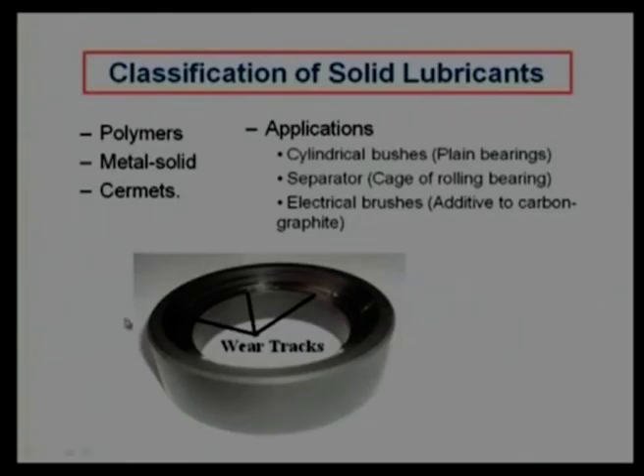When we talk about self lubricated, naturally the question comes whether they have a solid lubricant along with other composition. Maybe in this case it is carbon graphite mixed with antimony. Carbon graphite is used as a solid lubricant, whereas antimony is used to increase the conductivity and the impact resistance. But the problem with this kind of seal ring or block solid lubricant is that if there is wear, you can see the wear marks on it. If there is wear, then their intended function will not be fulfilled. They will start losing the intended function, and that will turn out to be a failure.